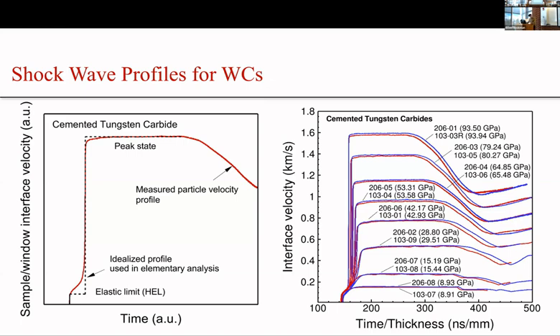In the figures on the right, we have shown the recorded shock wave profiles for all experiments for both grades, along with their peak longitudinal stress level. The stress level ranges from 9 to 100 GPa for both grades, and the HEL, the elastic limit, measured for the grade containing 3.7 percent cobalt binder is about 20% higher than that measured for the grade containing 6% cobalt, which means that the increase in cobalt content has decreased its elastic limit.